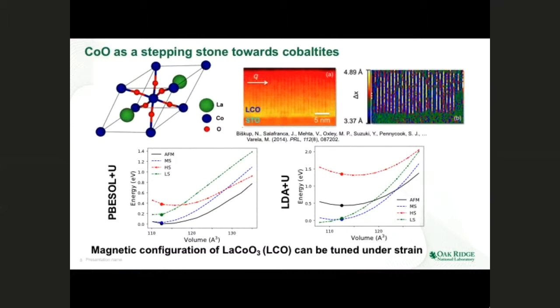So for lanthanum, I'll come to that again, but we are seeing that the lanthanum cobaltite, when it is grown under constant strain on the substrate, shows this kind of lattice modulation in this x direction in here, so that the lanthanum separations are being modulated.